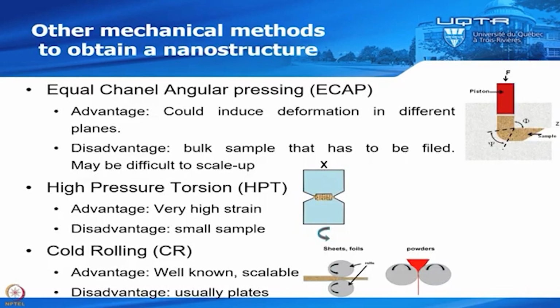So the other aspect that I would like to see in this talk is the other methods to obtain a nanostructure. So in the field of metal hydride, we have a couple of methods that are widely used by researchers. Maybe the one that is mainly used is equal channel angular pressing. So I will not go into detail, but here you have a piston, you have a die, and there is an angle in the die. So you take your sample, so this is your sample, and you push it through the die, so it has to go through this angle. And then by going through this angle, it will sustain a lot of strain.